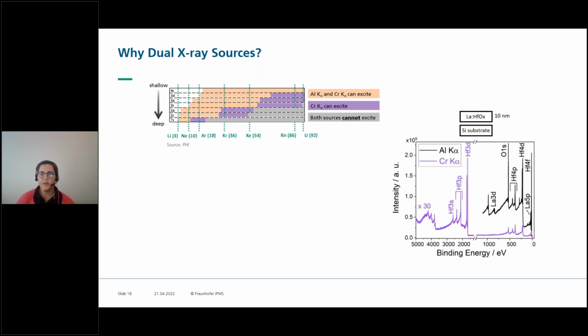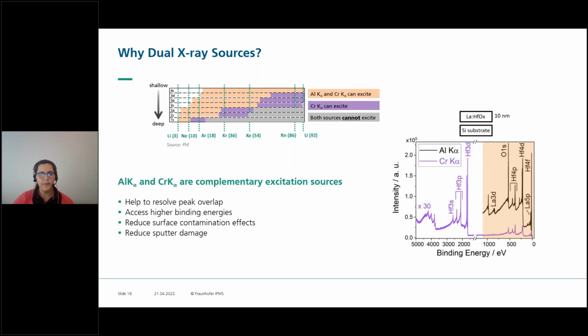On the right-hand side here, you see an example of a survey spectrum for 10 nanometer doped hafnium oxide thin film. On the x-axis is the binding energy, on the y-axis is our intensity. And the black curve here corresponds to a survey spectrum taken with aluminum Kα, and the purple with chromium Kα. Aluminum and chromium Kα are complementary excitation sources since they both help to resolve peak overlap, access higher binding energies, reduce surface contamination effects, especially if you use chromium Kα, and sputter damage.